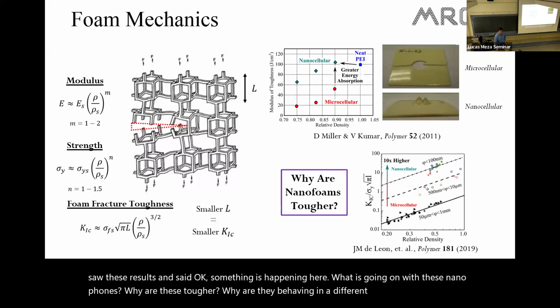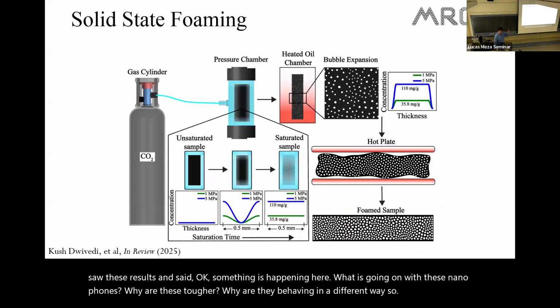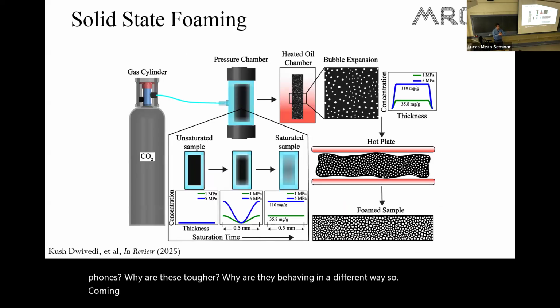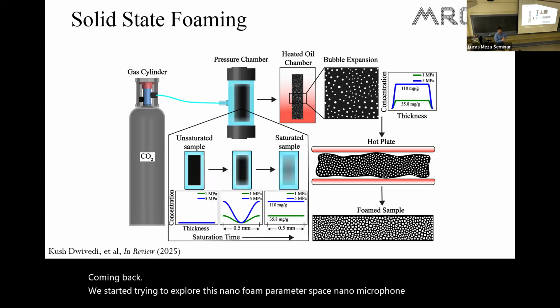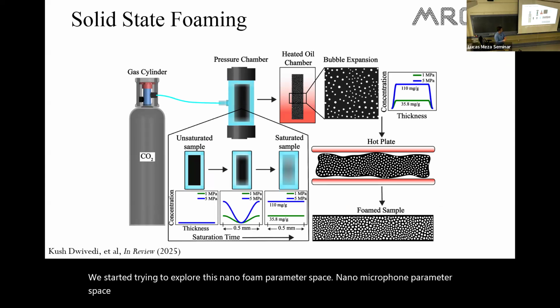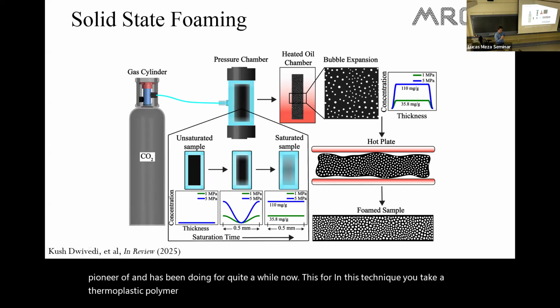So coming back, we started trying to explore this nanofoam parameter space, nano and microfoam parameter space. These materials are made with solid state foaming. This is a technique that Vipin is a pioneer of and has been doing for quite a while now. In this technique, you take a thermoplastic polymer, put it in a high pressure chamber, and saturate it with CO2. Generally, any inert gas sort of works. CO2 works better than most.